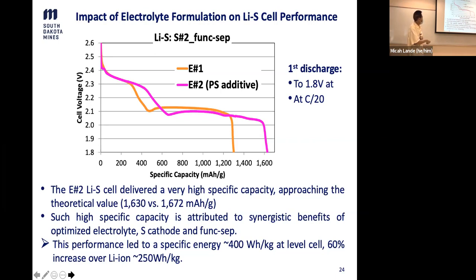When we calculate based on this performance, we can calculate the specific energy. Remember, the Army goal is for specific energy of more than 300. This cell performance actually translates into almost 400 watt-hour per kilogram at the real cell level, which is a 60% increase over lithium-ion. So that's another reason why lithium-sulfur is so interesting, because of the huge energy density gain. That drives the research into this chemistry.